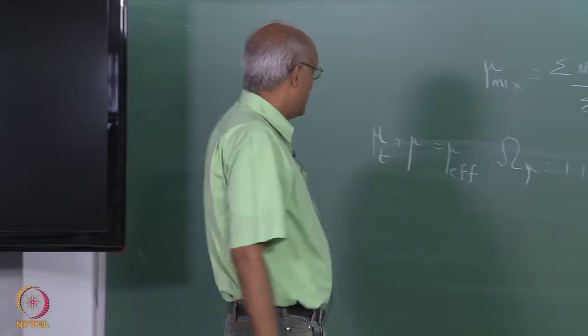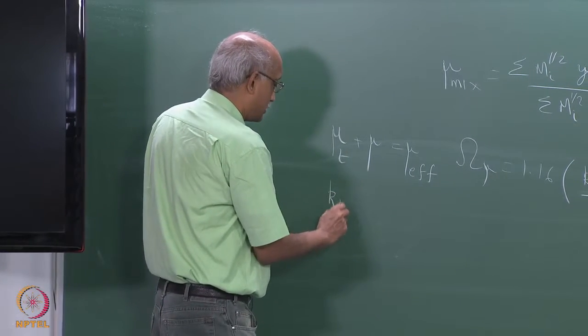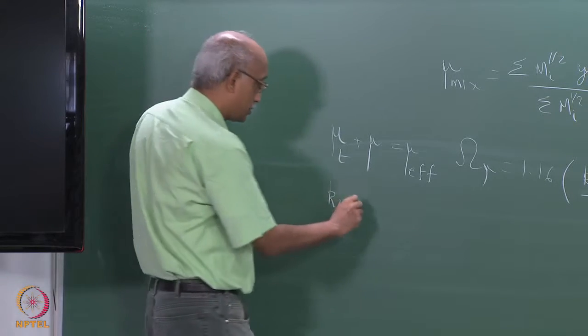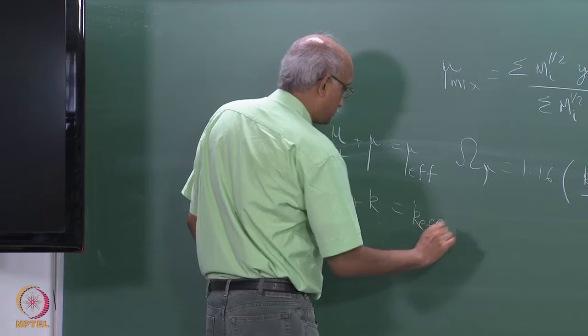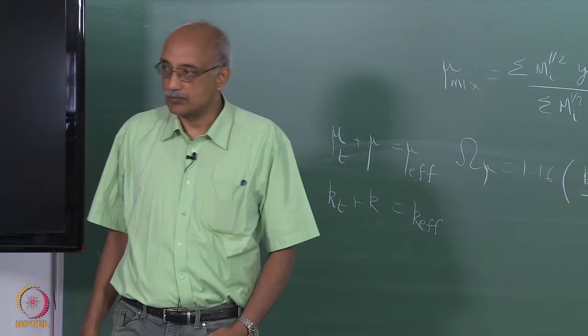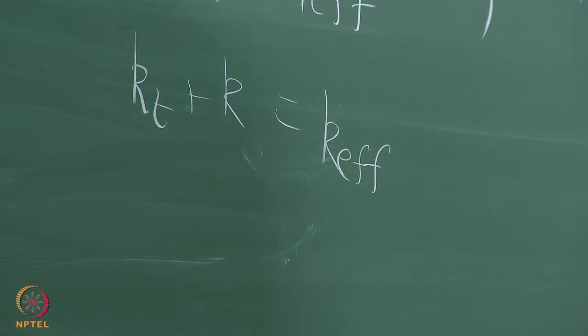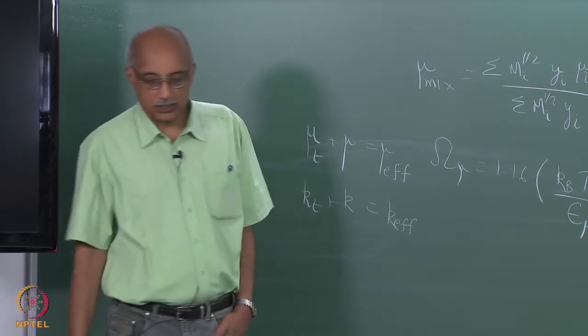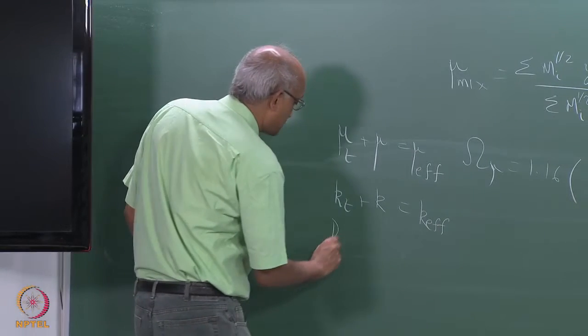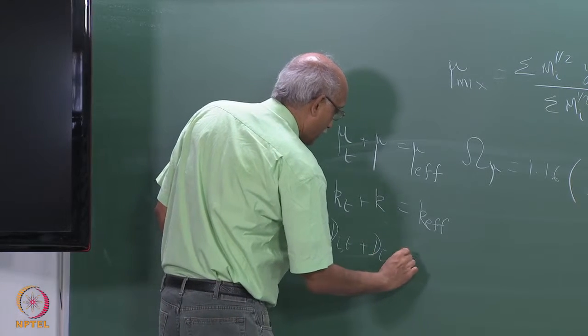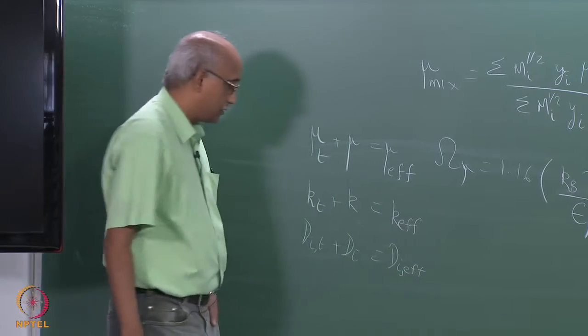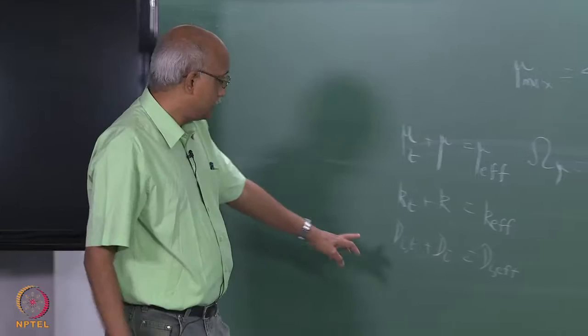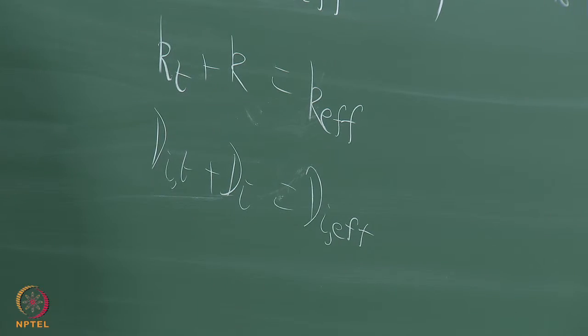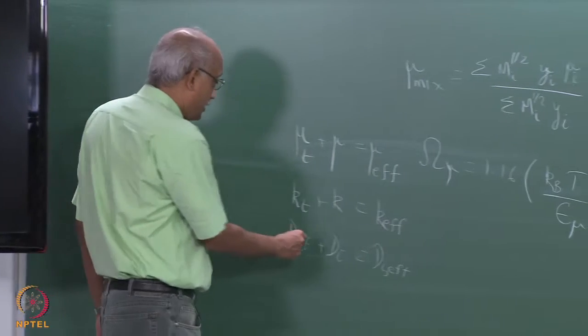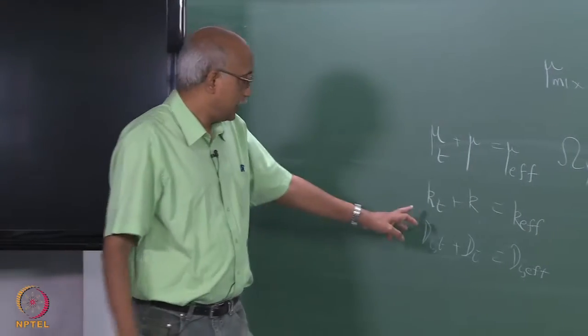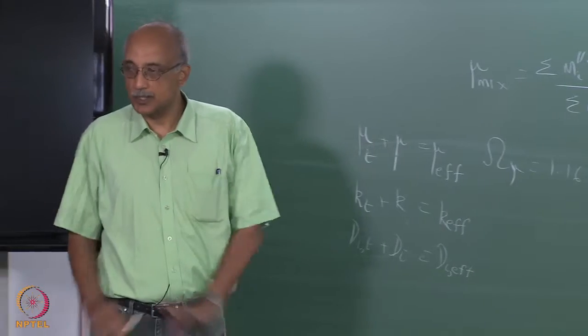And just like with viscosity, there is also a KT parameter, which is the thermal conductivity associated with turbulence, plus K will give you K effective. And by the way, the turbulence terms mu T and K T, and we will see later on that similarly for diffusivity, there is a DiT plus Di, which is equal to Di effective, where Di is the Fick diffusivity under laminar conditions and DiT is the turbulence enhanced Fick diffusivity. The interesting thing to note is that DiT has absolutely no relation to Di. Similarly, KT has no relation to K, mu T has no relation to mu. They are completely independent of each other.